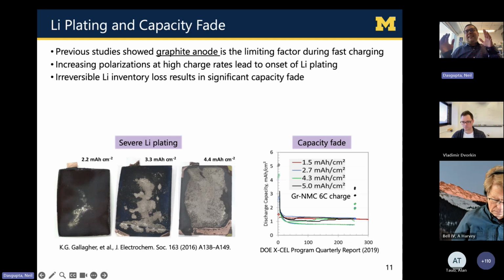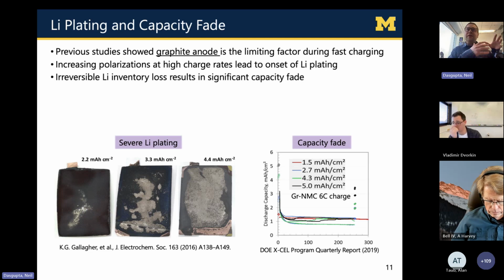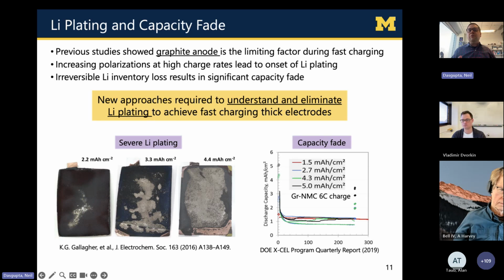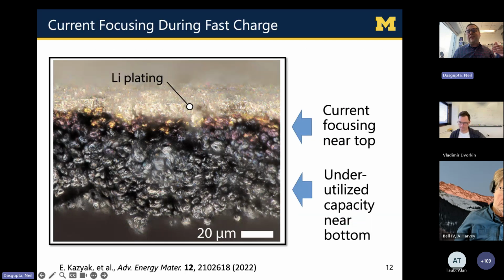And what that tells you is that's kind of the fundamental bottleneck of how thick a normal graphite electrode can be. I'm going to talk a lot today about not-normal ways of modifying the graphite to overcome this, but with your normal state-of-the-art graphite electrode, it's difficult to do this 10-minute fast charging with an electrode thickness greater than about 1.5 milliamp hours per centimeter squared. What that means is I can make a thin electrode that can charge fast, but I'm going to sacrifice that range. So really, we need new approaches to understand and eliminate this lithium plating to achieve fast charging while still enabling these thick electrodes.